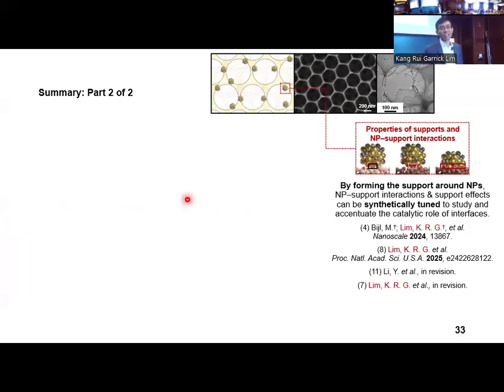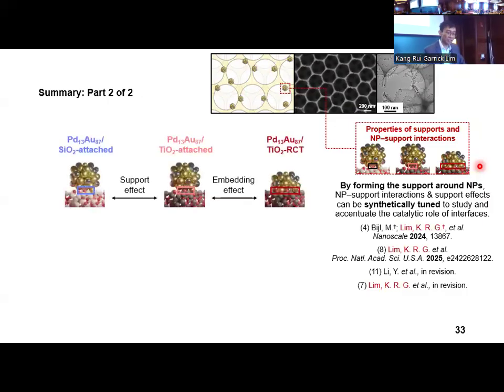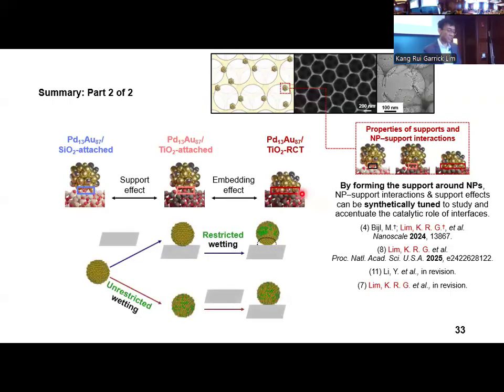This brings me to the end of the second half of my talk. I have showcased how the partial nanoparticle embedding feature in the RCT method can be used strategically to alter both catalytic and synthetic outcomes. First, we illustrate how partial nanoparticle embedding can accentuate catalytic contributions arising from the interface. Here, partial nanoparticle embedding increased the nanoparticle support interfacial parameter, which created more gold titanium interfacial sites for benzaldehyde adsorption and reaction at the interface.